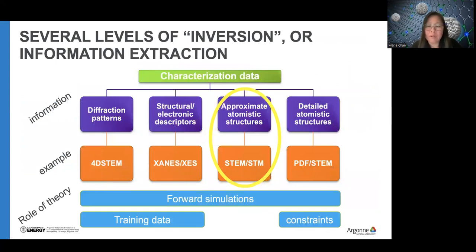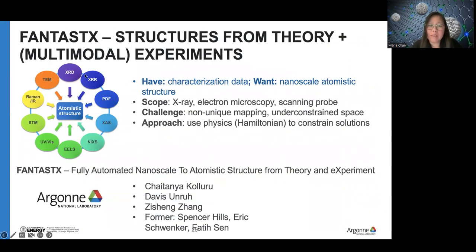That gave an approximate atomic structure, but really our holy grail is to spit out the 3D atomic structure from experiments as widely varied as X-ray diffraction, reflectivity, pair distribution function, X-ray absorption. I said it might not be possible with X-ray absorption alone, but what if we have XRD and XAS? What if we have Raman and XAS or other combinations? So this push towards doing multimodal experiments has been there for the past 10, 15 years. Progress is slow, but we're slowly getting there.